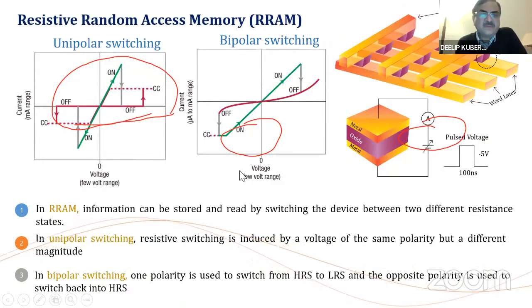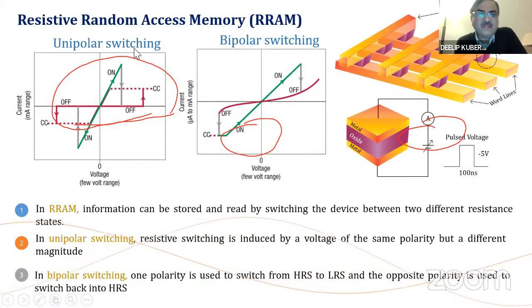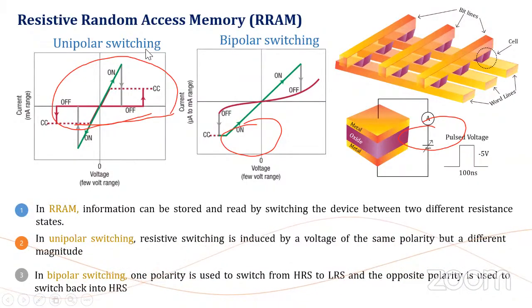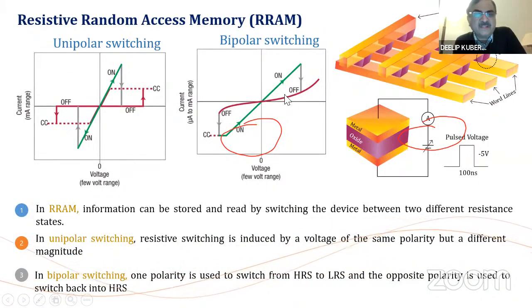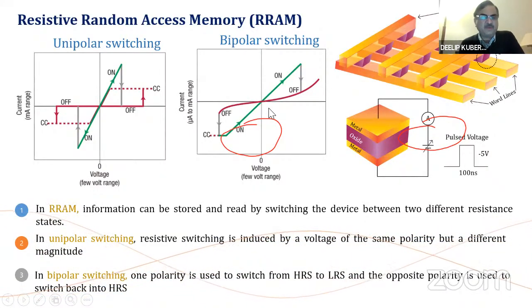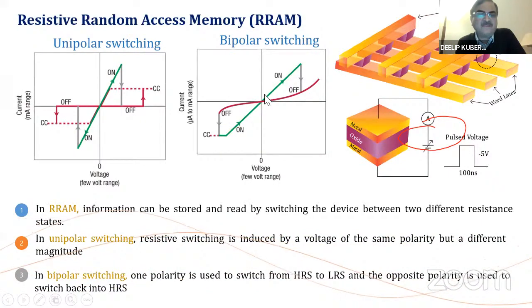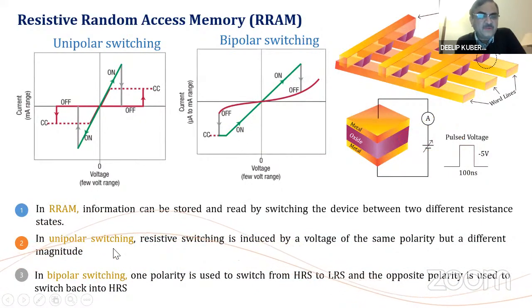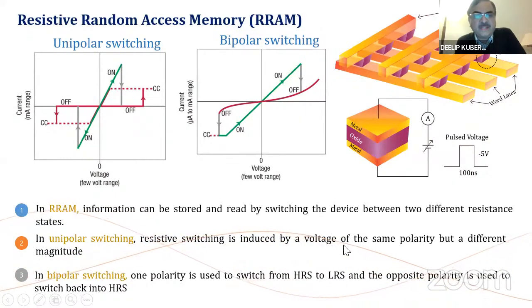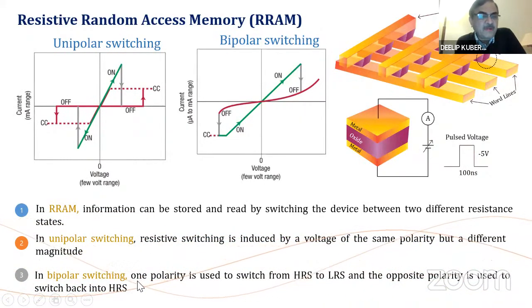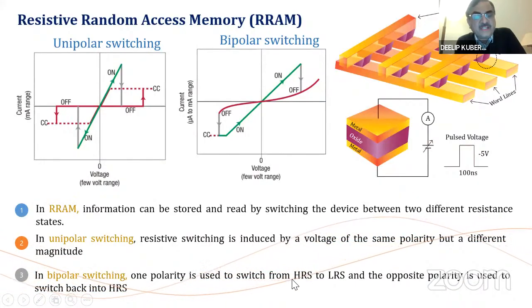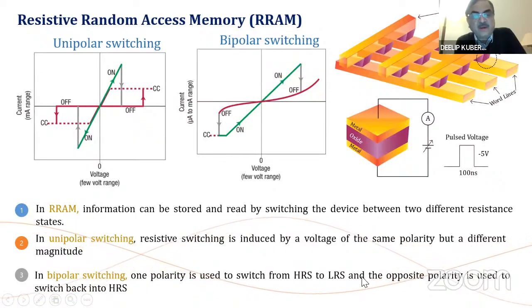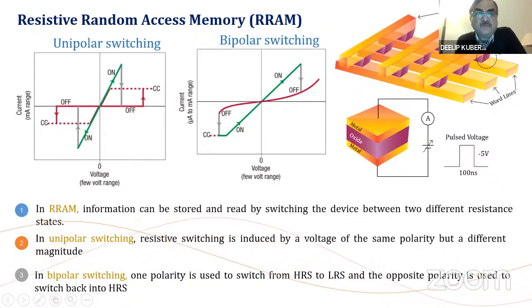Now, in resistive random access memory, you can do two types of switching. One is unipolar switching, another is bipolar switching. This is a bipolar switching here. You can switch the applied bias voltages in both ways, plus and minus, and you can do the bipolar switching. In unipolar resistive switching, it is voltage of the same polarity but of different magnitude. But in bipolar switching, one polarity is used to switch from the HRS, the high resistance state, to the low resistance state, LRS, and the opposite polarity of the bias voltage is used to switch back from LRS to HRS, so you have to switch the applied voltage polarity.